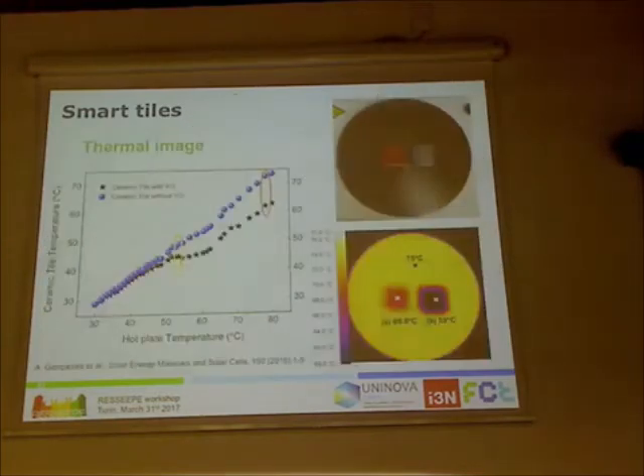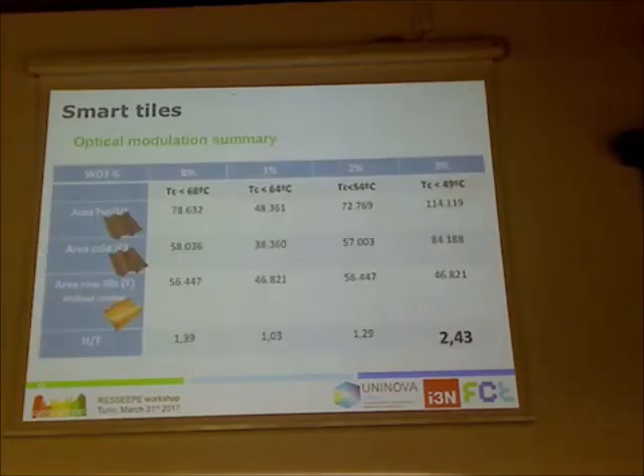I'll finalize by saying something about stability. I already said we can solve the problem of adhesion, but we still have the problem of stability, because when you expose vanadium oxide VO2 to the environment, it starts to oxidize and will change after some time to V2O5. So what's missing here is a kind of protective layer over the coating to avoid direct exposure of VO2 to the environment. Otherwise, it will transform after some time into V2O5 and we'll lose the thermochromic property—we lose the effect we want. This needs to be addressed, and most of the time it's addressed with a polymeric coating on top of the thermochromic layer.